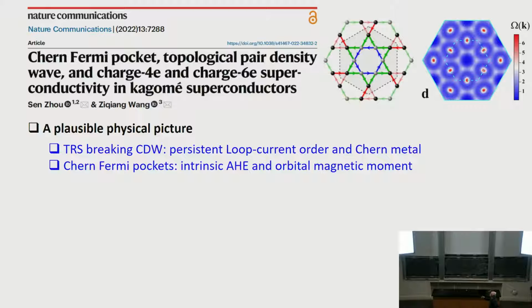The loop current state looks like this. So the proposal is the time reversal symmetry breaking CDW state is a state in which there is an order of persistent loop currents. I just drew one like that. And because you're on the Kagome lattice, I'll show you time reversal symmetry breaking leads to a topological state. And that is a Chern insulator, but doped with some carriers, so it's called the Chern metal. And what you see here is this Chern metal has what's called Chern Fermi pockets, Fermi surfaces, and that exactly coincides with where the Berry curvature concentrates. So it can explain this anomalous Hall effect through the orbital magnetic moment.